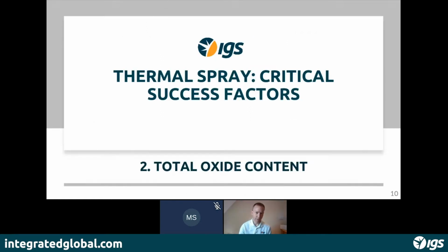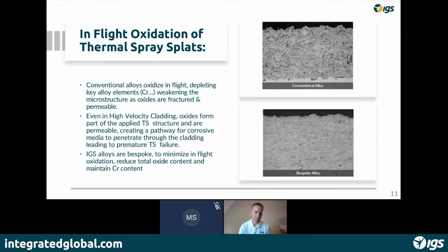barrier. The other challenge with thermal spray is it's an aggressive process for the alloy itself. So we're melting a material and then we're projecting it through ambient conditions to the substrate. So it's going to react with the oxygen in the atmosphere. Now we need to ensure that the alloy is sufficiently modified so that we have the right components once it's applied onto the surface. And we also need to prevent the oxides creating a weakness within the inherent applied system.